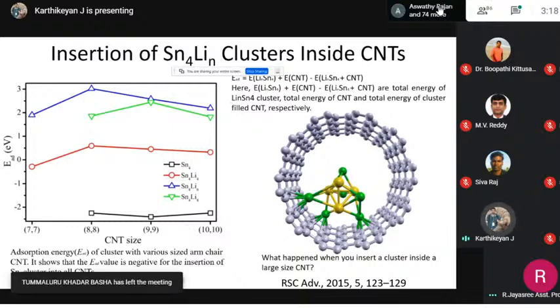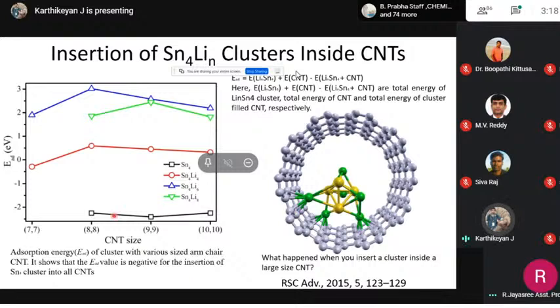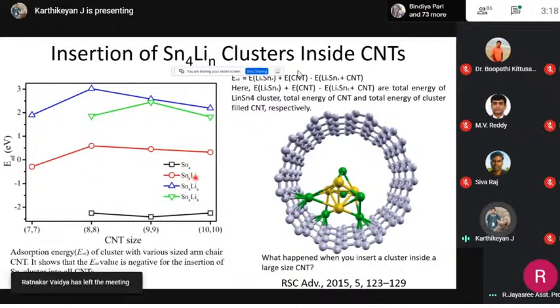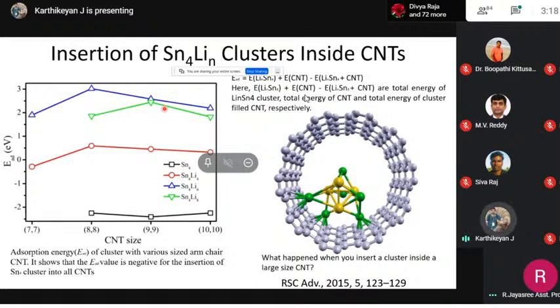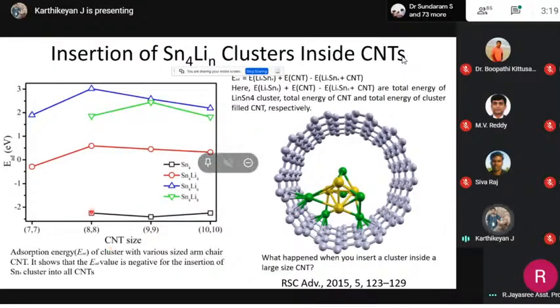I have chosen armchair-type CNT because it is metallic. We have also tested the same with chiral and zigzag CNTs, and we can see that for Sn4Li4 and Sn4Li6, the 8x8 CNT is more stable, but only for Sn4Li8 the 9x9 CNT is stable. So in future calculations, if I mention the Sn4Li8 cluster, it means it is inserted inside a 9x9 CNT. For other clusters, I have taken the 8x8 CNT. What will happen if you put a very small cluster inside a CNT? It will stick to one side of the wall. Since not all the atoms interact with the CNT, it gives a very low adsorption energy. For the optimum size, it gives more adsorption energy. So we have taken the optimum size for insertion of lithiated tin clusters inside CNT.